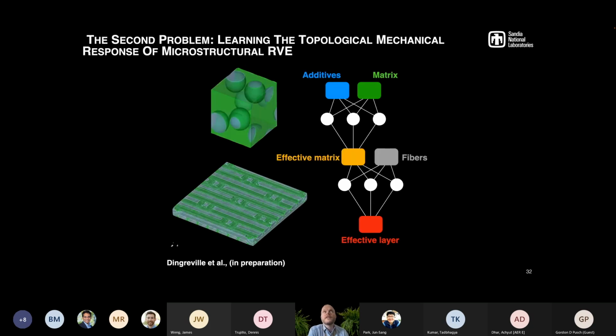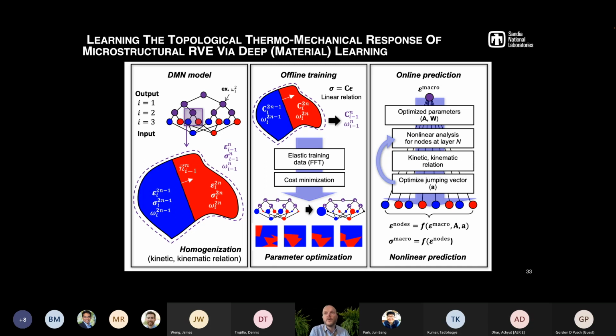In our case, we're interested in learning the mechanical behavior of composites across scales, where you would have some deep learning architecture where you can feed in the individual components, either inclusions and a matrix, or at a different scale, a matrix and fibers, and be able to predict the effective response across scales. So in this case, we borrowed some work done by Liu and coworkers at ANSYS, called the deep material network, where you can learn the topological thermomechanical response of an RVE using a deep neural network. What I'm showing you on these slides are the components of how it works.